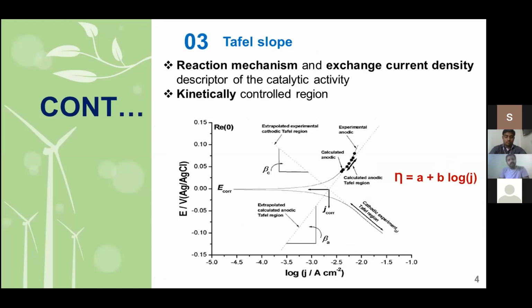The third one is on the Tafel slope. Not only must the electrocatalyst possess low overpotential, but it must also have a low Tafel slope value. So what kind of information can we get from the Tafel slope? We can determine the reaction mechanism and how much current has been exchanged between the electrodes. Through this, we can determine the catalytic activity of an electrocatalyst. So how can we determine this Tafel slope? By means of polarization curves.